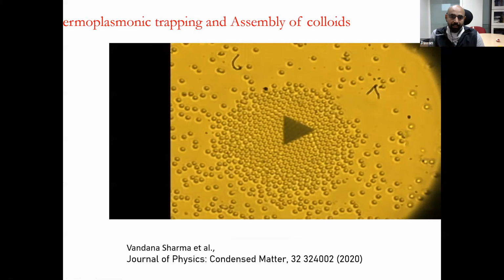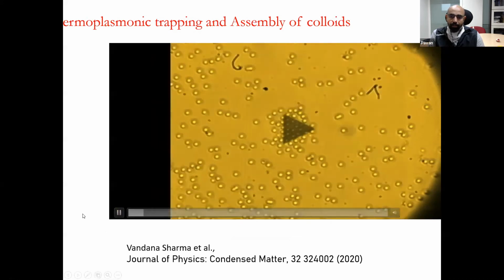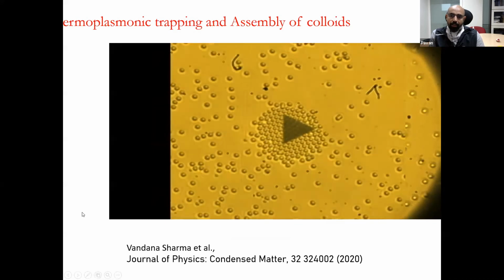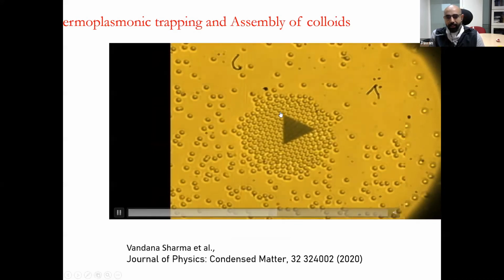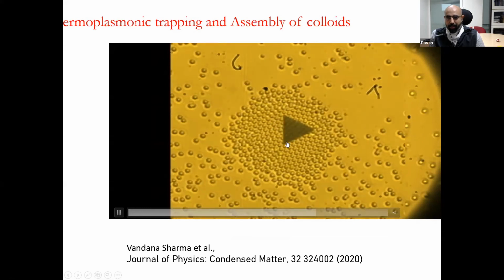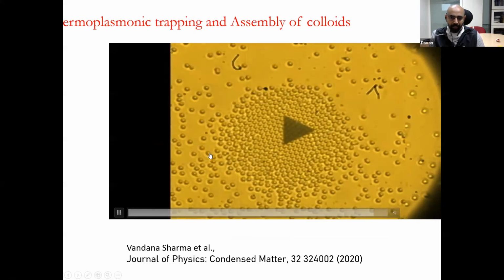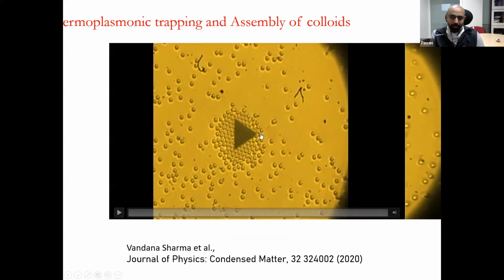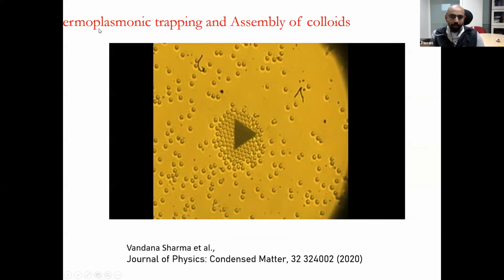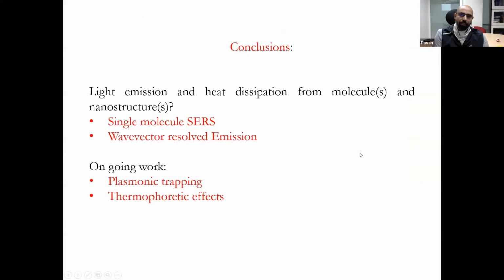In this particular case, it is silica particles, which are roughly around 2.5 to 3 micron in diameter. But we are also now performing experiments with nanoparticles which are roughly around 200 nanometers or something like that. This gives rise to beautiful two-dimensional crystals of colloids, all facilitated by the optothermal fields which we have generated. So the prospects are many, and what I have essentially talked about, to conclude, is that light emission and heat dissipation from molecules and nanostructures can facilitate single molecule surface enhanced Raman scattering.